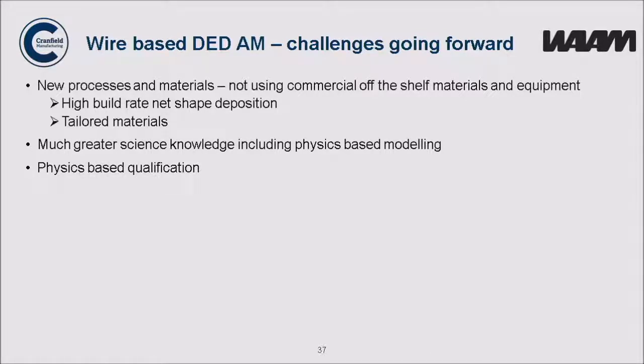Physics-based qualification. So qualification is a major issue, and our approach is going to be to use a physics-based approach. If we try to use a standard welding approach, this will never work. In a particular part, we might have thousands of different process parameters. There is no way you're going to write a process specification for that. And there is no way you're going to go and do 100 different parts under the same conditions and take the statistically worst sample if you're only going to build 10 of them in the first place. So we have to have a different approach to qualification.